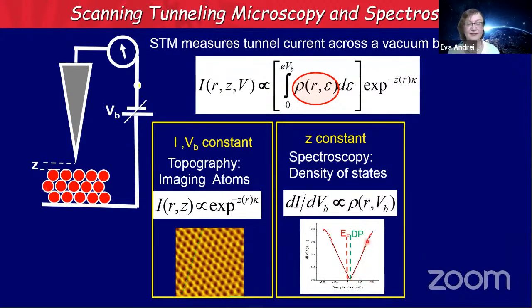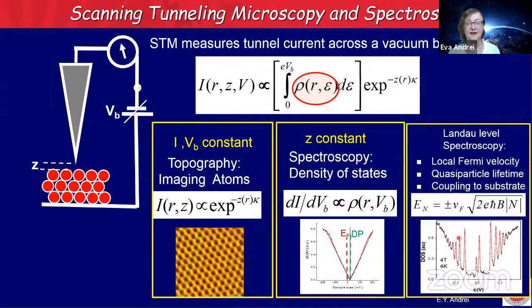So this is what it looks like for graphene, exactly as predicted theoretically. You have a linear density of state here, which vanishes at the Dirac point here in green. And the Fermi energy in scanning tunneling microscopy is the zero of energy. So by gating your sample, you can separate the Fermi energy physics from the Dirac point physics. And of course, then you can apply a magnetic field, and here pop out the Landau levels. And by fitting the energy of these levels as a function of their level index, 0, 1, 2, 3, 4, or as a function of magnetic field, you can extract the local Fermi velocity. So there is a lot of things that we can do just with scanning tunneling microscopy and spectroscopy.